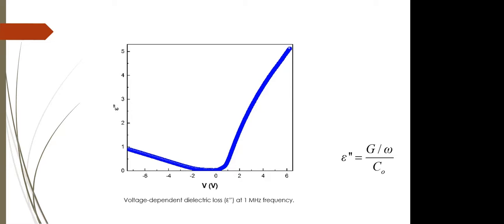As can be seen from the graph, an inverse behavior is observed between the dielectric loss and dielectric constant. It's observed that the dielectric loss value decreases with increasing voltage in the inversion region. A band bending occurs from 0.2 volt and a rapid increase is observed in the accumulation region after 0.4 volt.